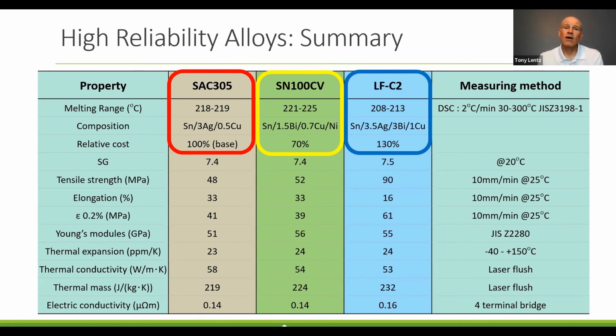SN100CV melts a little higher than that, 221 to 225, although it reflows in a similar profile to SAC305. And then LFC2 actually has a slightly lower melting point. It melts between 208 and 213, so roughly 5 degrees lower than SAC305. So you can actually run your oven a little bit cooler with LFC2. And then the compositions are shown there and relative costs.